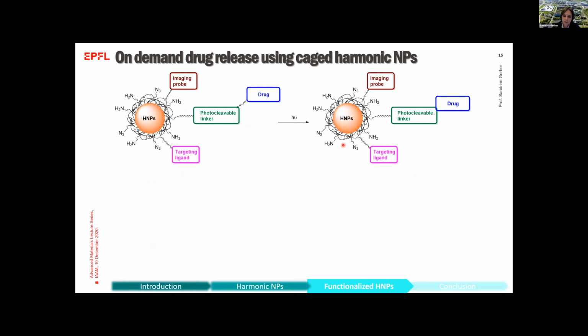Finally, the last aspect we explored was the possibility to use the harmonic signal generated by the nanoparticles to trigger the release of caged molecular cargoes introduced at the surface of the nanoparticles, giving the possibility for decoupled imaging and photoactivation protocols. This was previously reported for example for up-conversion nanoparticles, but this had never been developed for harmonic nanoparticles before.